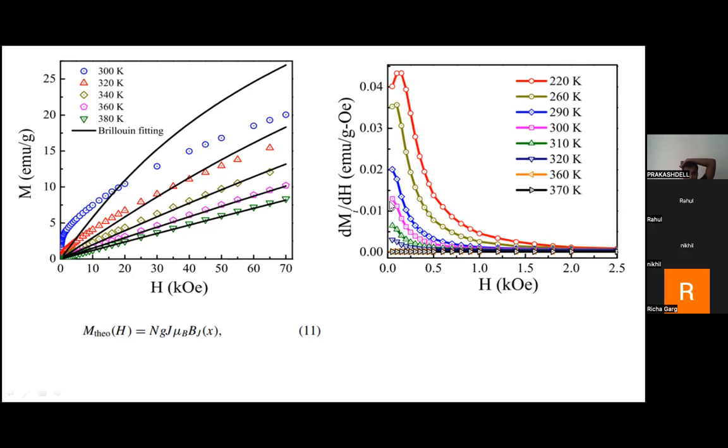And this is another beautiful theoretical claim. If you take the first derivative of the magnetization data, this M-H plot, from above the Griffith phase and below the Griffith phase, once you really reach the Griffith phase, you will find linearity. It's very surprising. You don't find any such tendency if you are dealing with a conventional ferromagnetic material which doesn't possess this phase. So this is another trademark signature, how you can confirm whether the Griffith phase exists in your system or not. Very simple, but a very nice way to unambiguously check.